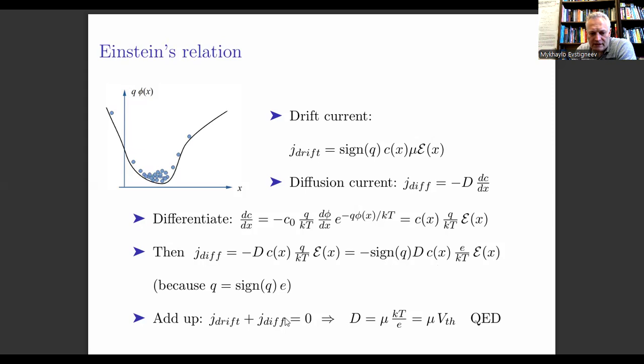All right, so what remains is to add up the drift and the diffusion currents. That is this line plus this line, adding up to 0. This is the drift current here, plus the diffusion current, they add up to 0. So the sign of q cancels out, c of x cancels out, and what remains is the diffusion coefficient multiplied with q over kT must be equal to the mobility. So the diffusion coefficient is the mobility times the ratio of thermal energy divided by the elementary charge, or the diffusion coefficient is the product of the charge carrier mobility, electrons or holes, times the thermal voltage. And this completes the proof of Einstein's relation.